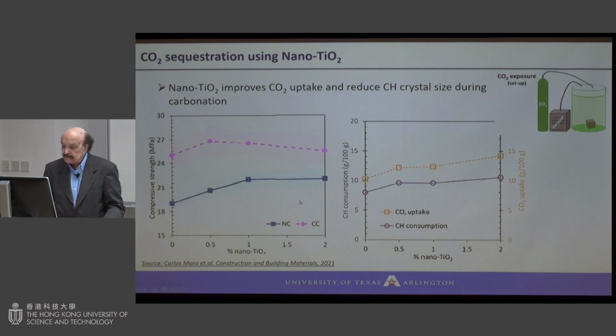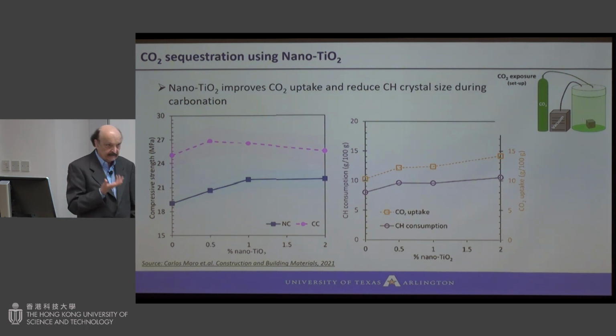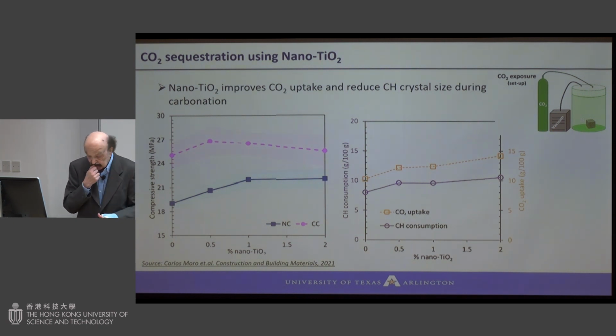And if you look at the CO2 uptake, or CH consumption, it increases up to about 1%. Now why does titanium dioxide, after carbonation, increase CO2 uptake? They speculated that the addition of titanium dioxide reduced the size of the calcium hydroxide crystal. And if the calcium hydroxide crystal size is smaller, they can take up more carbonation.